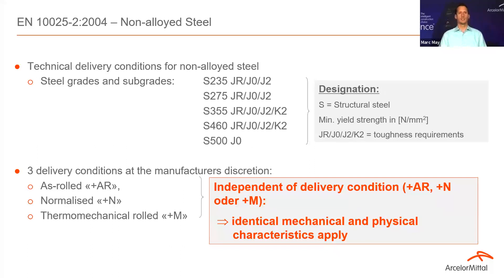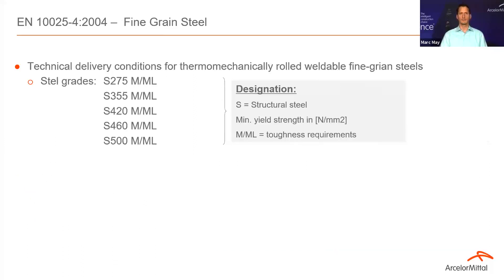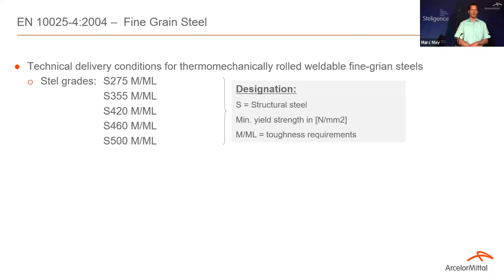This is part 2 of EN 10025, the non-alloyed steel part, with three delivery conditions defined: as-rolled (+AR), normalized (+N), and thermomechanically rolled (+M). The mechanical and physical characteristics are independent of the delivery condition — it is only an indication of how the producer makes the steel. We typically produce thermomechanically rolled steel, so +M. Part 4 of EN 10025 covers thermomechanically rolled, weldable, fine-grained steels. The ML subgrade has even tougher requirements — 20 joule at minus 30 degrees.